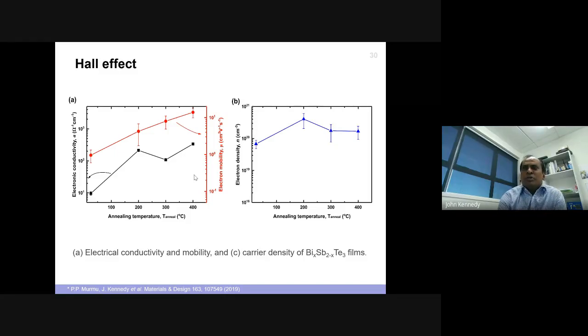And if you look at the Hall electron density, the number of N, which is a key factor, if we look at the effective mass and carrier concentrations in the previous formula, they are reasonably within the error bars as well. So that's good. This also shows that it is an N-type material, so it's N-type conductivity.